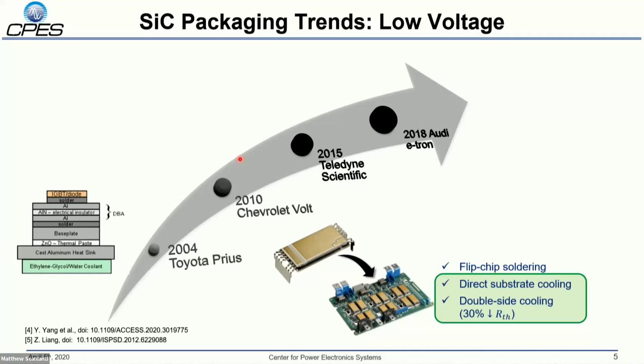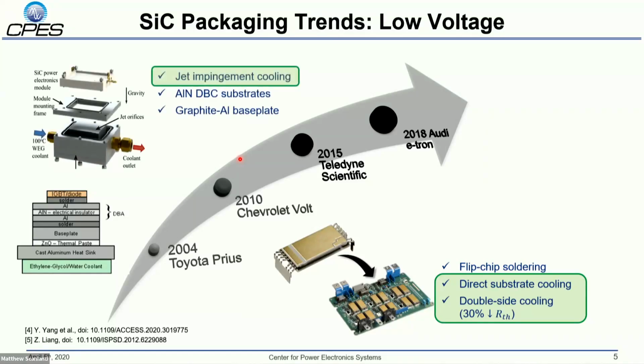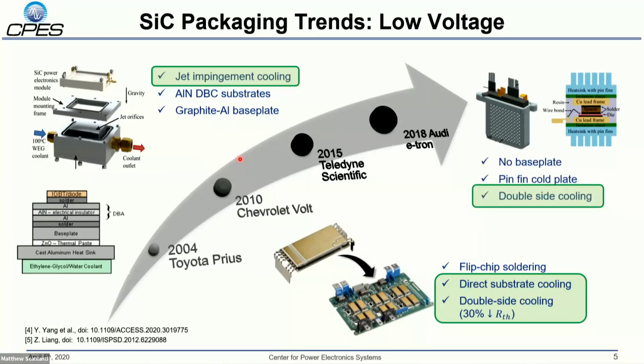And I think this has been motivated largely by the rapid adoption of 1.2 kV SiC within the automotive industry. So in 2004, we had fairly straightforward packages that were being used in the Toyota Prius. By 2010, in the Chevy Volt, they had moved to double-sided cooling and direct substrate cooling. By 2015, we saw introductions of jet-impingement cooling on electric vehicles. And most recently in 2018 on the Audi e-tron, they've gone with a double-sided, actually, immersion cooling system. So a very clear trend in the low voltage path.